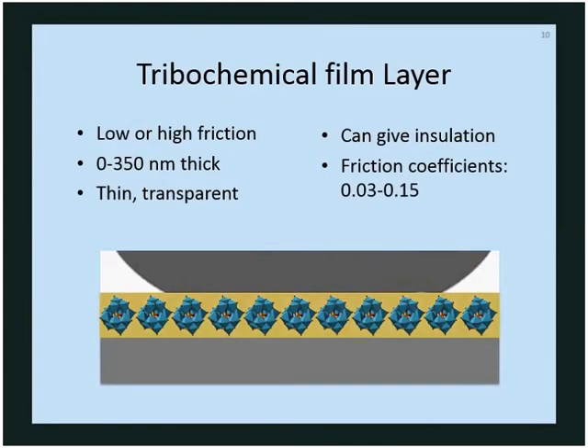In hopes for a tribochemical film layer to form during testing, they can be either low or high friction. In this project, it was of course desired to have low friction in order to improve fuel efficiency, etc. And they are thin and transparent, only 0 to 350 nanometers thick. And then they can give insulation between the steel ball and flat.